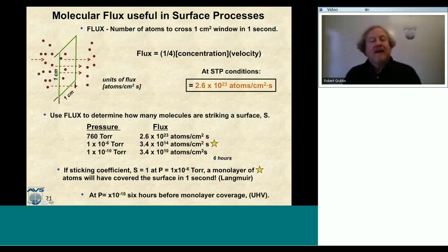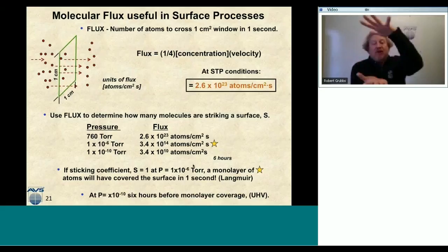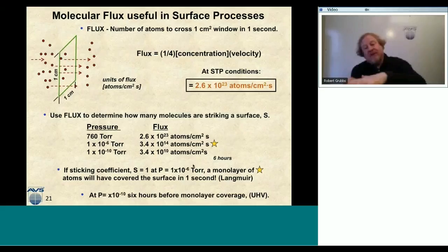Now, if the sticking coefficient is 1 and the pressure is 1 times 10 to the minus 6 torr, a monolayer of atoms will have covered that surface in 1 second. I hope that's clear. And that is what's going to define something called the Langmuir. The Langmuir is a unit of exposure.